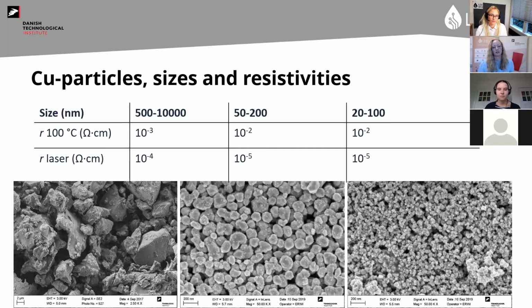a laser or a xenon lamp to cure your material, and you want to cure it because you want a dense layer, then you can actually settle with larger particles because the resistivity is lower if you just heat it up at 100 degrees. However, if at your facilities you have the possibility to use a laser or a xenon lamp, it will be better to use the smaller nanoparticles because they will give you a lower resistivity. And that's also something we have to think about.